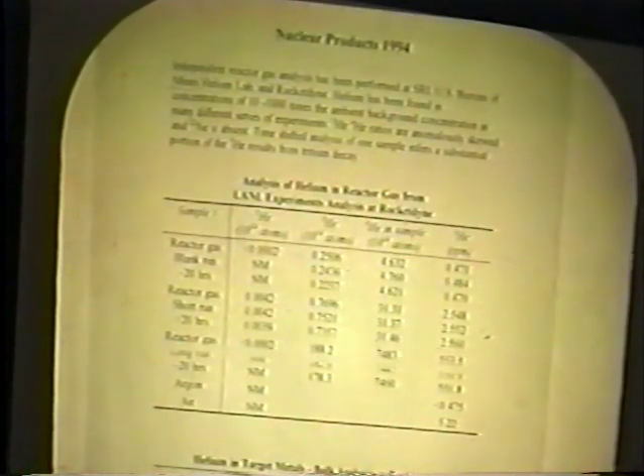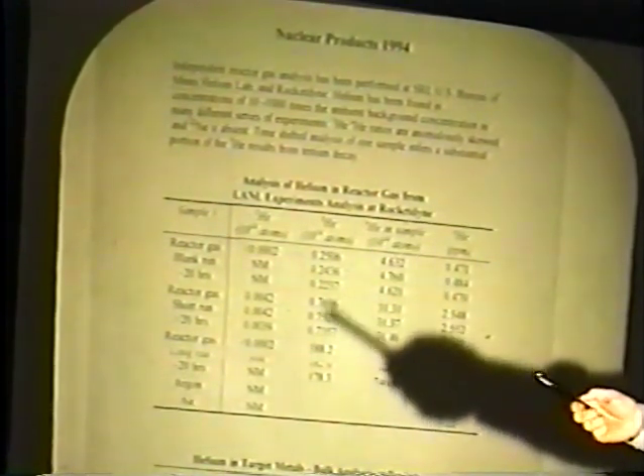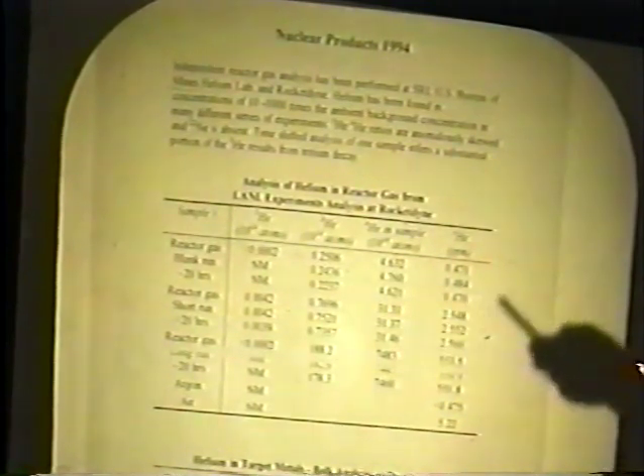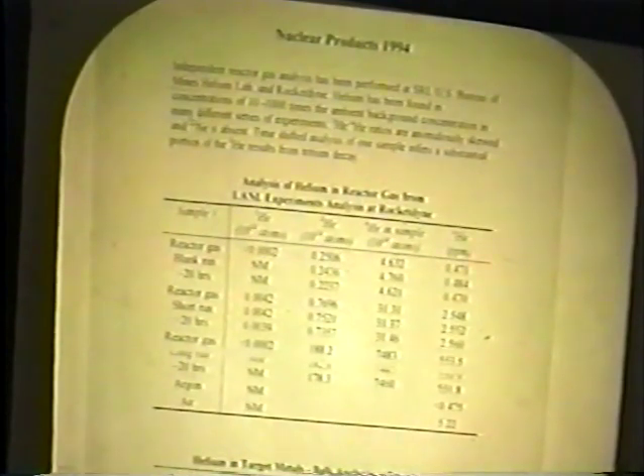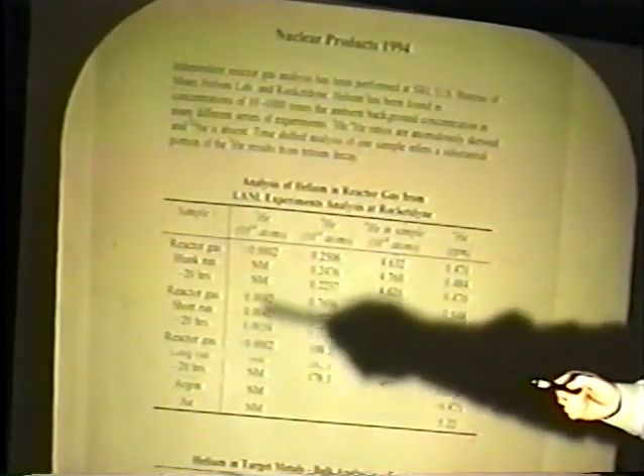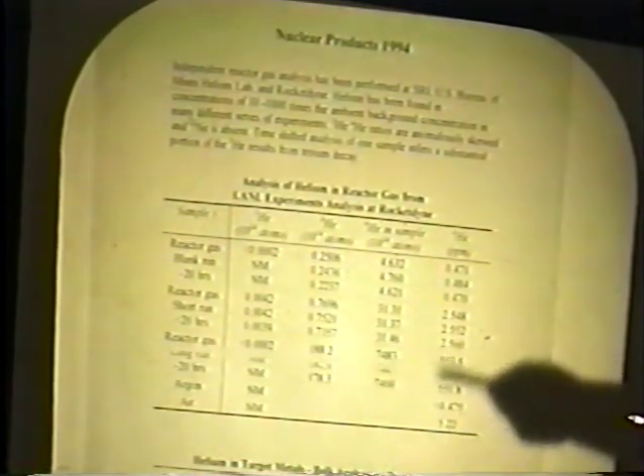And lo and behold, this top one was a gas sample from the reactor which didn't produce any heat effects, and it had a very low helium concentration. This one, a run of a little under 20 hours that we call short, had produced a small amount of helium-4. Curiously, it had produced a fair amount of helium-3, which we found quite mysterious. I'll talk to you about that in a minute. And then this other one, which was a long run, had produced 500 parts per million helium-4, with very low helium-3.